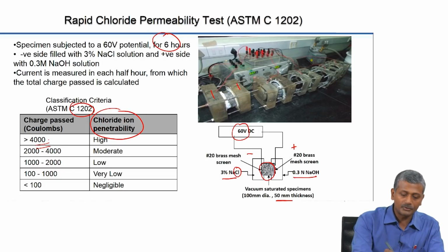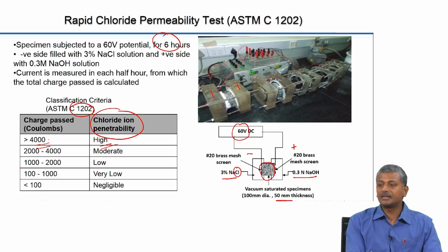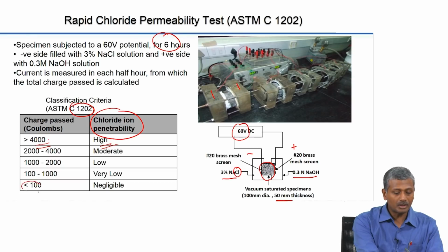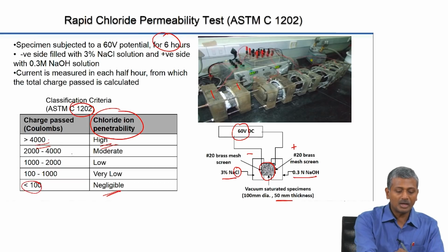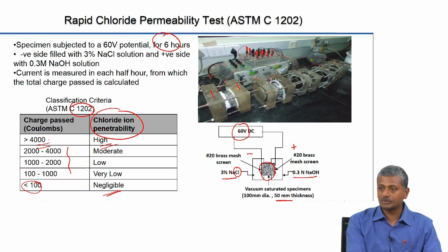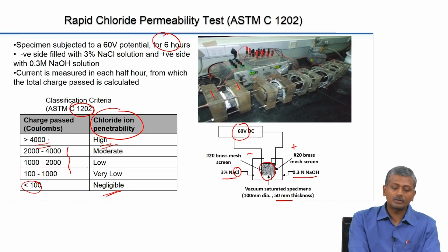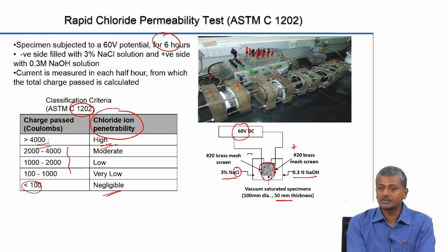If it is more than 4000, your chloride ion penetrability is deemed to be high. Less than 100, it is negligible. Then you have these intermediate ranges in between. 2000 to 4000 is moderate, 100 to 1000 is very low, and 1000 to 2000 is low, okay.